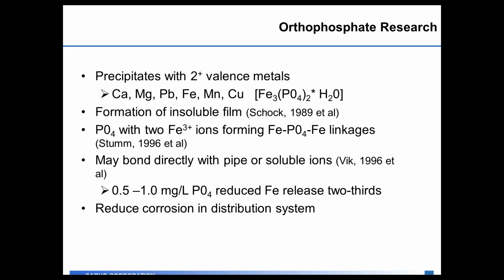Michael Schock has done a lot of research showing that formation of insoluble film with the phosphate products out in the distribution system. Some of the research shows that as little as half a part to 1 milligram per liter as orthophosphate reduces the amount of iron that would release from a cast iron pipe by 2/3. But overall, the whole body of research for orthophosphate shows that they reduce the amount of corrosion issues that you have in the distribution system. So they'll eliminate a lot of lead and copper issues and help with iron issues in the distribution system.